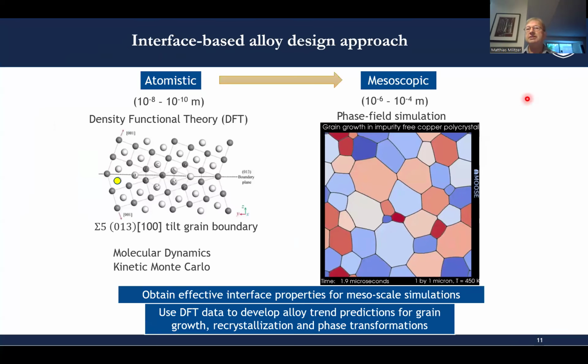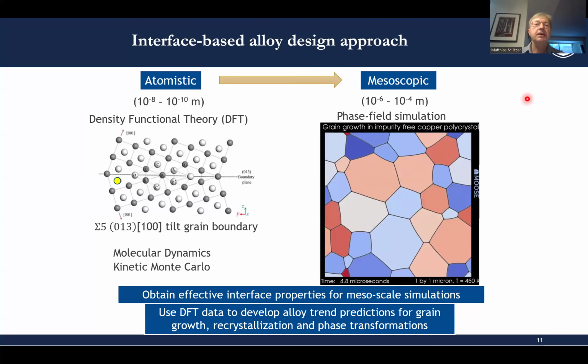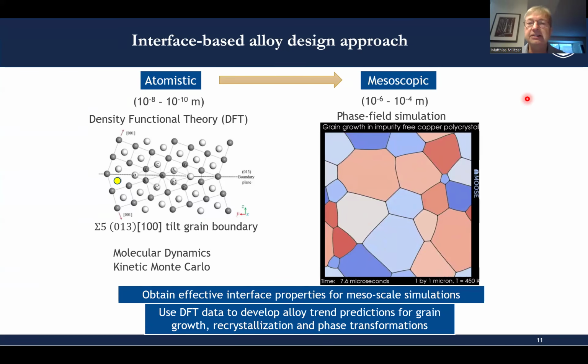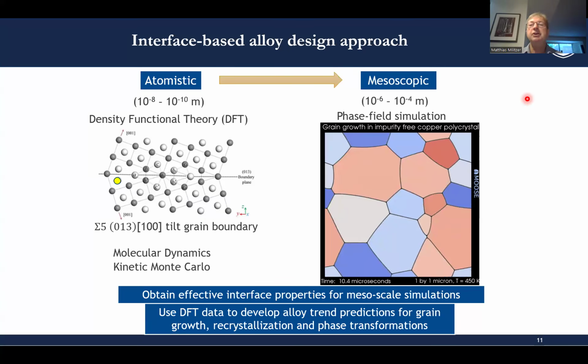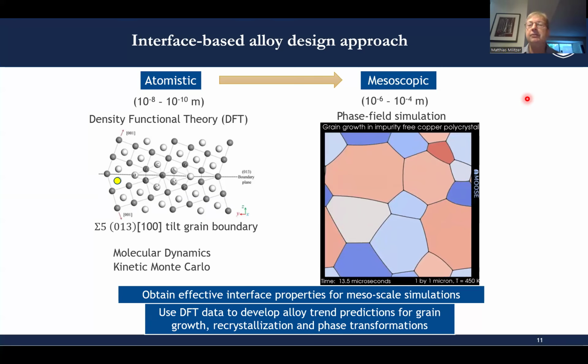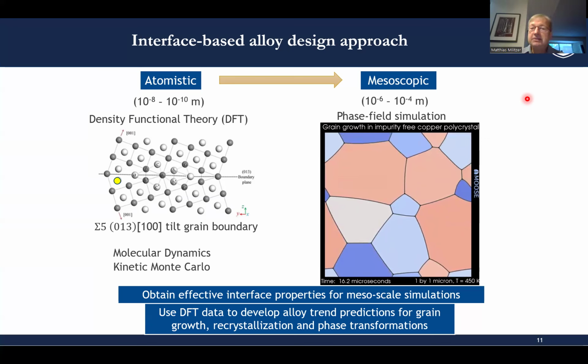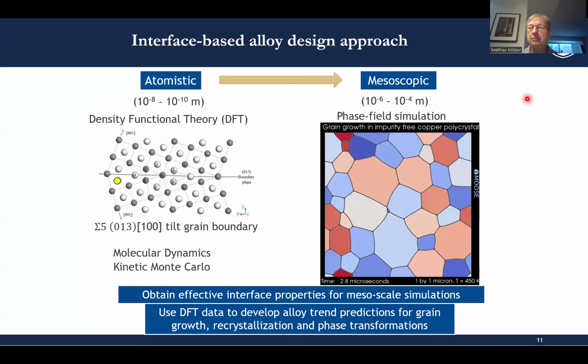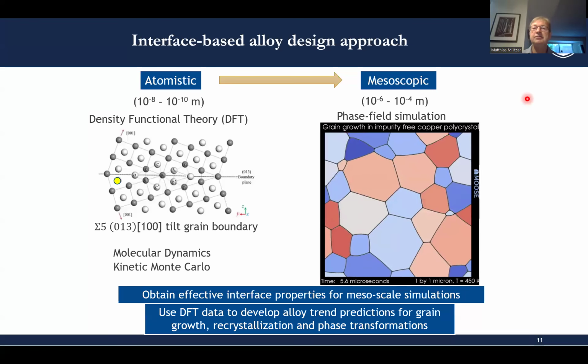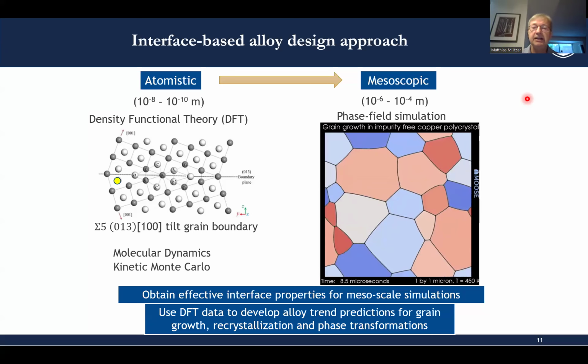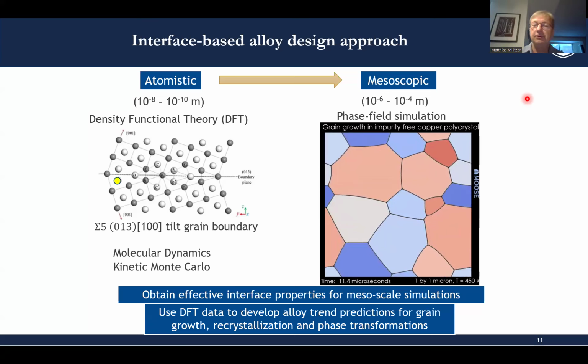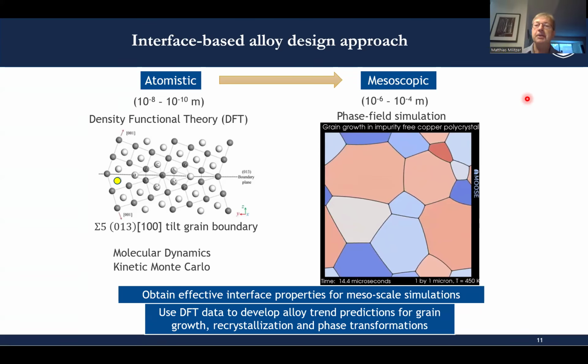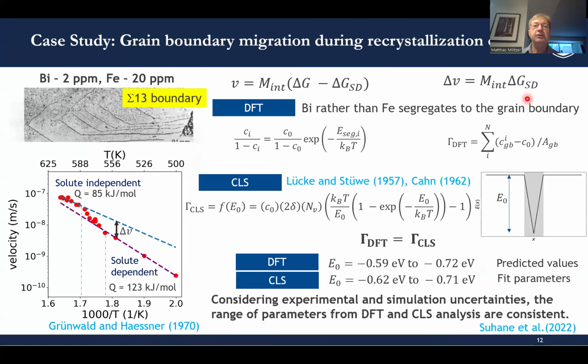Okay, now we have all this atomistic simulation data. What can we do with it? Basically, the idea is, if you look at a phase field simulation, you run the grain growth simulation in the background. We need interface properties to populate the phase field model. Maybe we can use information from atomistic simulations to find these properties, or at least some of those, and then use DFT data to develop at least trend predictions in terms of alloy development for grain growth, recrystallization, and phase transformation. What we propose here, I would like to illustrate on a case study that deals with grain boundary migration during recrystallization of gold. It has nothing to do with steel, obviously.